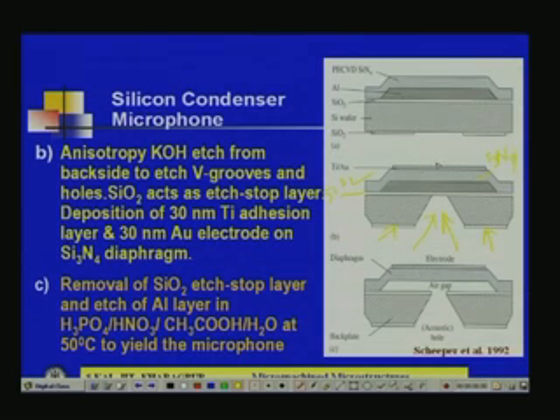Now, there is the titanium gold layer, and if you etch this complete aluminum, that is why I told you aluminum will be the sacrificial layer, then you will get the diaphragm, and this is the acoustic hole, and this is filled with air. Now, just like a microphone, this is one electrode, which is titanium gold, basically a gold electrode. If you speak something or some acoustic signal is applied in this hole, then accordingly it will vibrate. So, this electrode will move, and below that this nitride is given in order to have structural stability. Only this gold film will not be stable at all. Basically, the diaphragm is made of silicon nitride. Silicon nitride is the diaphragm, and gold titanium is the electrode.